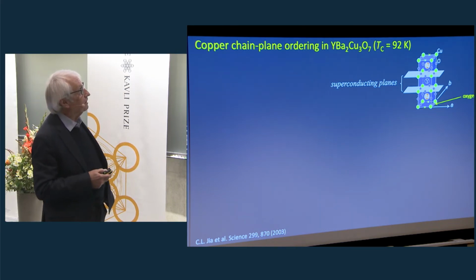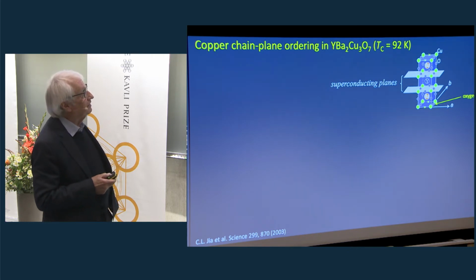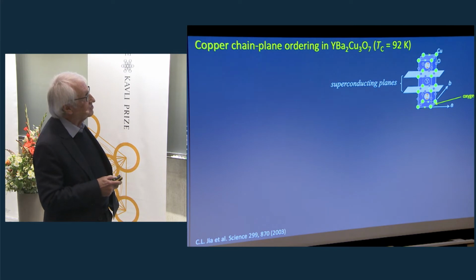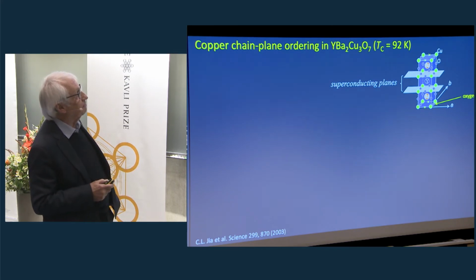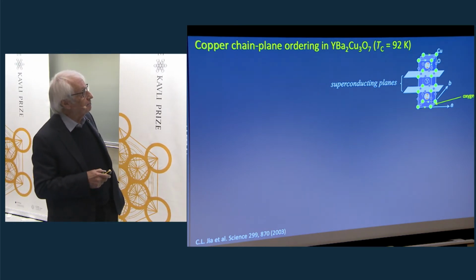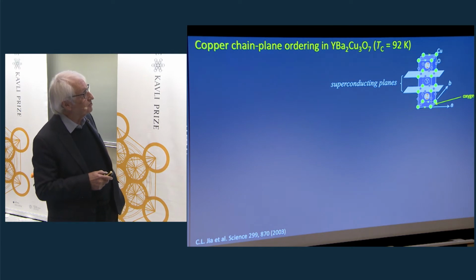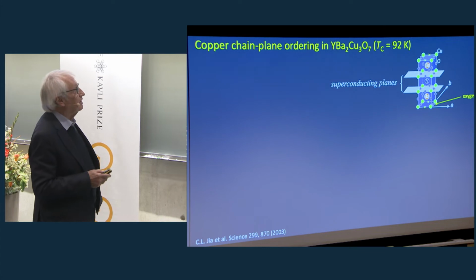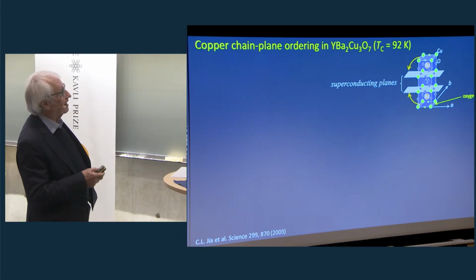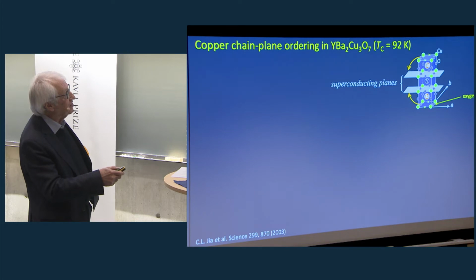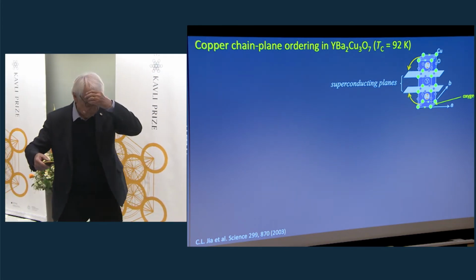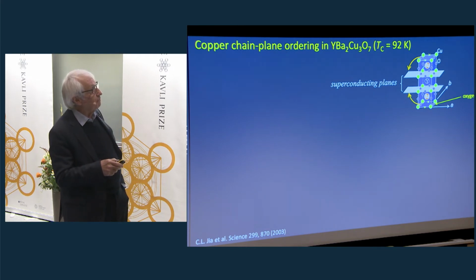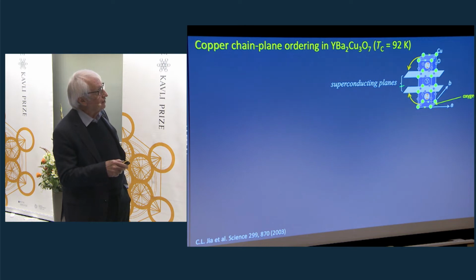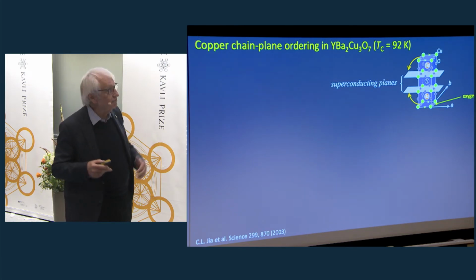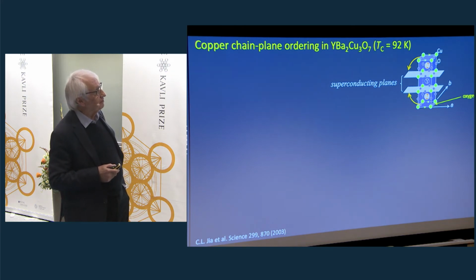This here is a ball and stick model of yttrium barium copper oxide. And we have 3 perovskitic unit cells which together form the unit cell of yttrium barium copper oxide. We see here the barium, yttrium, barium. Green are the copper atoms, and blue the oxygen atoms. So it's well accepted nowadays that the superconductivity is hole superconductivity along these planes here, and the doping of these planes with holes goes via these copper-oxygen chains, which is an elementary factor in this type of superconductivity.